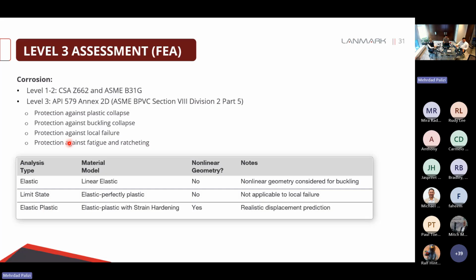In the case of corrosion, CSA Z662 and ASME B31G are just useful for doing level 1 or level 2 assessment. Actually, ASME B31G provides some general guidelines for doing level 3 assessment, but it is not something detailed or step-by-step. So because of this, we are adapting the stress analysis framework in API 579 Annex 2D for doing level 3 assessment over corrosion.